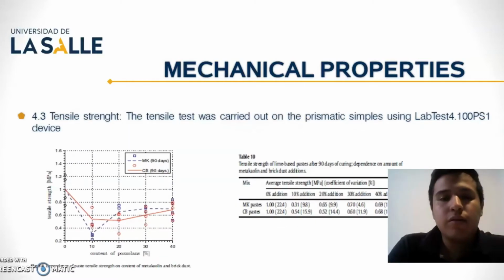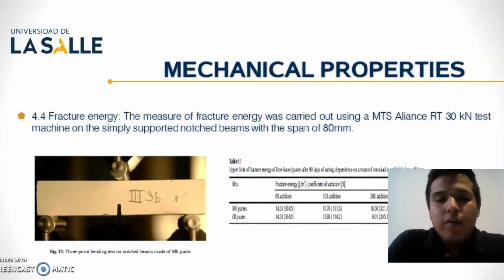The inhomogeneous structure of the binder and differential hardening result in the development of a non-uniform strength field. However, further research focused on the distribution of individual phases and their properties is needed in this area. The obtained results are in agreement with the findings of Nishikawa, who investigated the fracture mechanical properties of cement paste without aggregates. They concluded that any inclusion, even unhydrated clinker within the paste, can increase the energy needed for crack propagation.